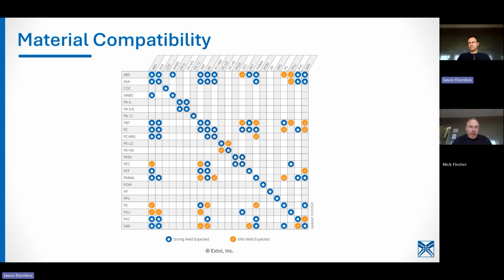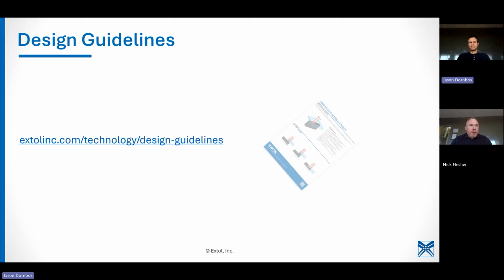Most all within a family can be welded. We do have 2 categories there, with a mid weld expected. In other words, your strength might be 40, 50, 60% of parent material. I'm surprised we haven't been asked about how much strength we get. We typically get that. We can pretty easily accomplish 80 to 95% weld strength with laser plastic welding. You really have a low heat affected zone, but you can get that strength really high because of how we're heating it while we're applying the pressure, and in a way that the plastic doesn't break down.